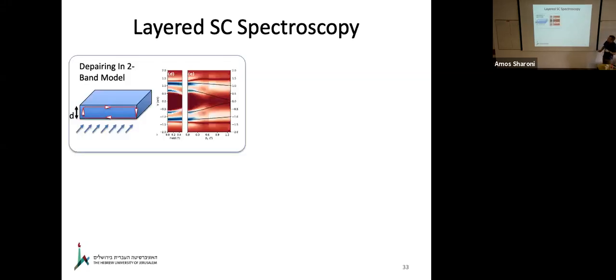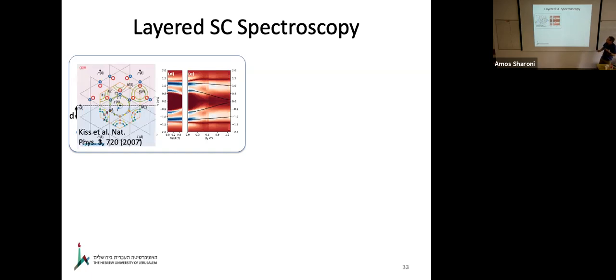Now I'm going to show you in 60 seconds everything my group did which is unrelated to defects. We studied the two gaps of niobium diselenide, and we showed that if you apply an in-plane magnetic field, you can actually differentiate them. One evolves differently than the other because its kinematic properties are different. The carriers are different. We could identify that one gap is related to a certain band, the selenium band of this material, and the others are related to the niobium bands.